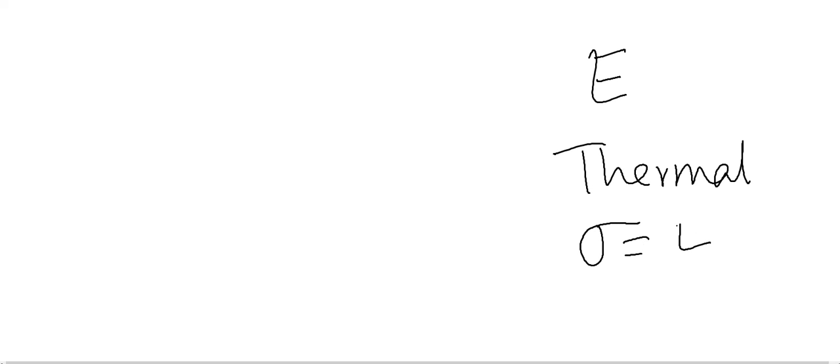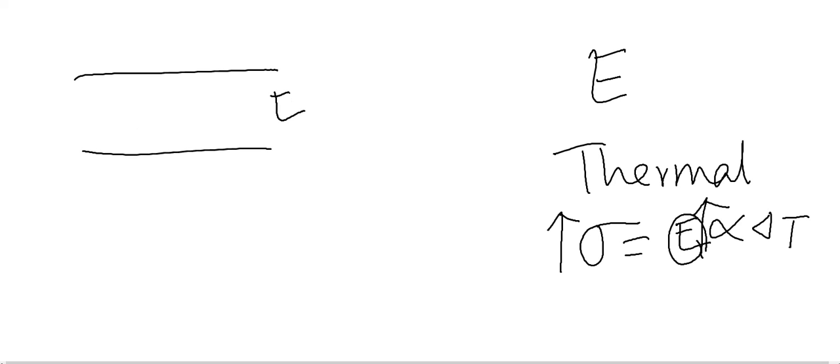So we know the modulus of material. If the modulus is very high, thermal crack is a problem, because developed thermal stress is E alpha delta T. If your E is high, developed stress will be higher. So if you use higher E, a stiffer material, that is bad for thermal. At the same time, if your E is less, due to applied load, your tensile strain will be high.